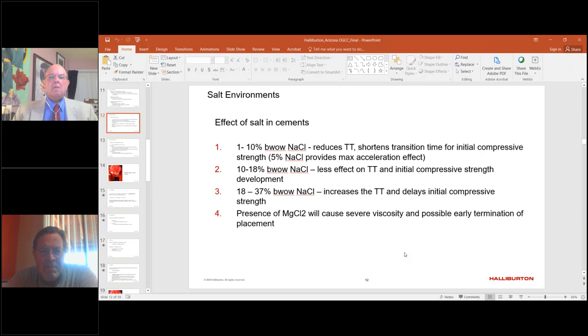So if we're designing for static salt, we would normally look at about 10 to 18% by weight of cement sodium chloride. Somewhere between 1 to 10% will accelerate. Anything over 18% will delay. It'll be liquid for days, possibly longer. And hence we would look at about 10 to 18% by weight of cement sodium chloride incorporated into the cement, which by incorporating it into the cement slurry means that you're not going to dissolve it as you go past the static salt because it's already about the same concentration.